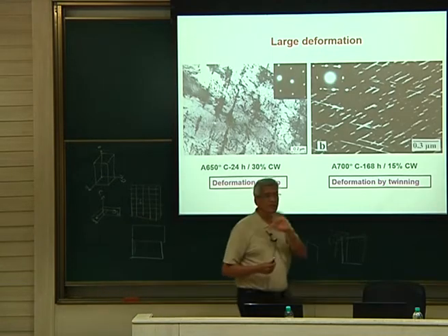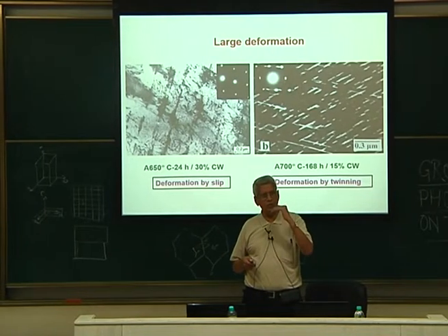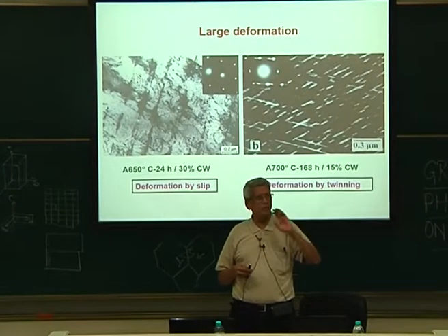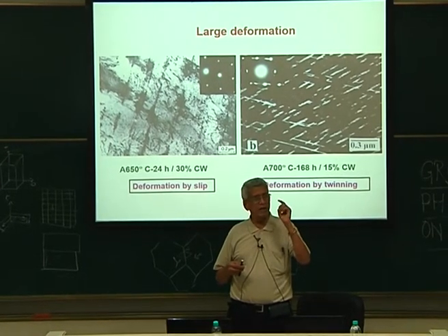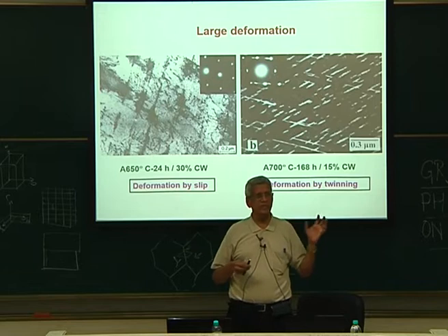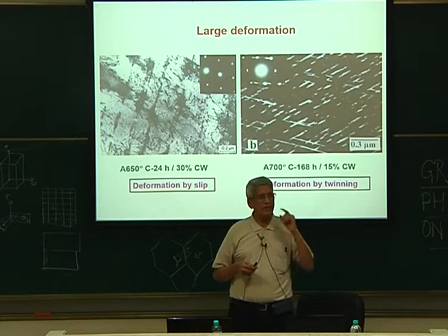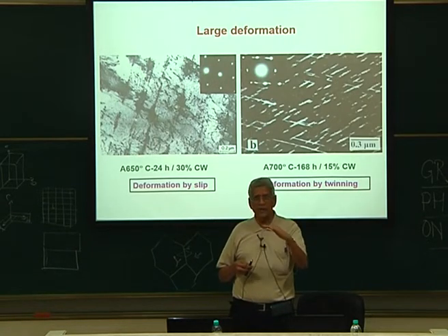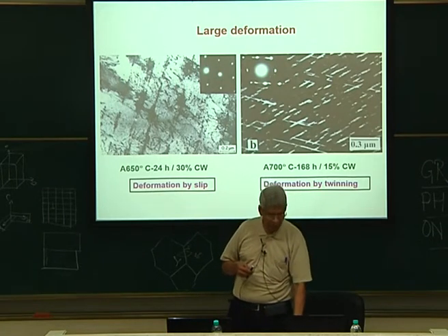So essentially, the mechanism in this alloy system when the precipitates are very small is groups of perfect dislocations passing through. When the precipitate size is large, normally what we expect in most cases is that when the precipitates become large, looping forms. Here we do not see looping, here twinning forms. The reason is that as soon as the dislocation comes and touches the particle, since the fault energy of the precipitate is very small, it splits into partials.